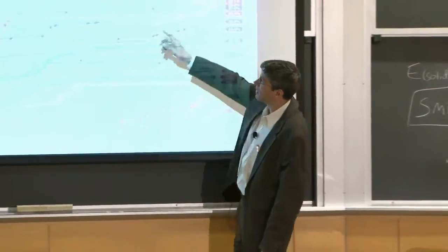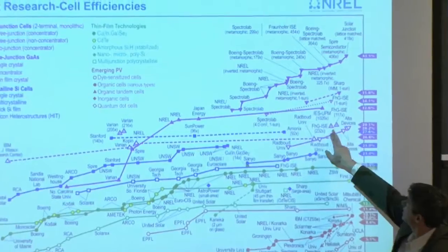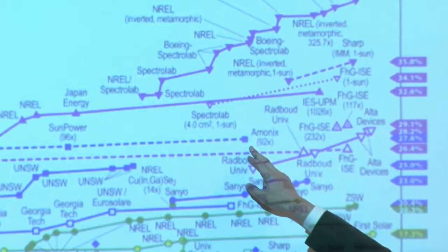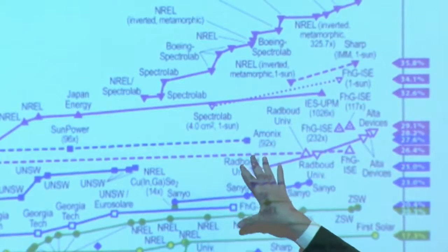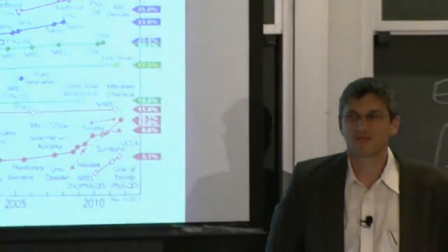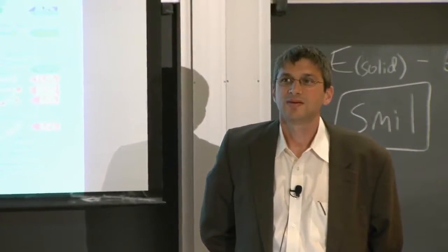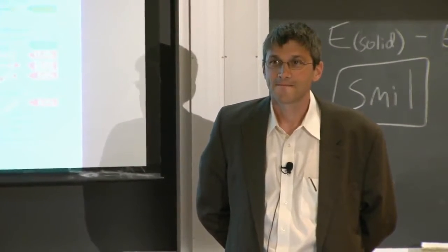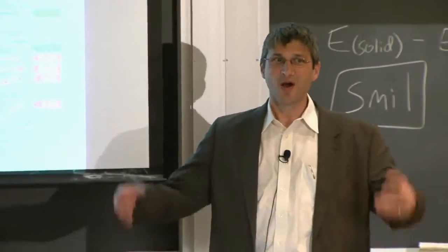And for monocrystalline silicon, which is the best you can do, that's here, you see that we're pushing what I'll show you is close to the theoretical limit of how efficient this process can be. But that's 27%, you see. But if I buy it, 18% is the best you can get on the market of monocrystalline, right? Now, why is there such a difference between the research cell and what I can buy today? Well, cost of mass manufacturing, but then you also have the binning process. You have internal defects from industrial mass production. Yeah. Scale up is hard.